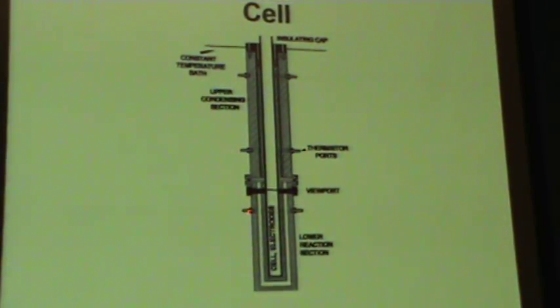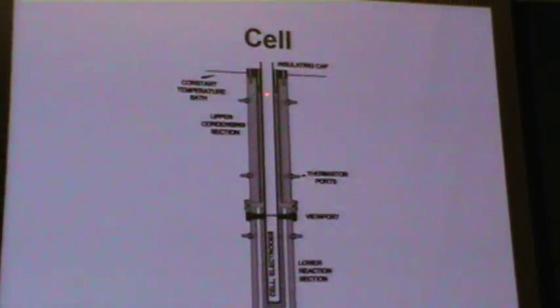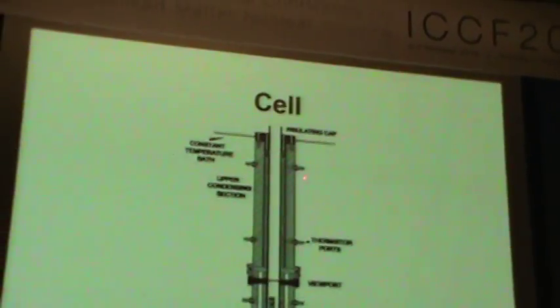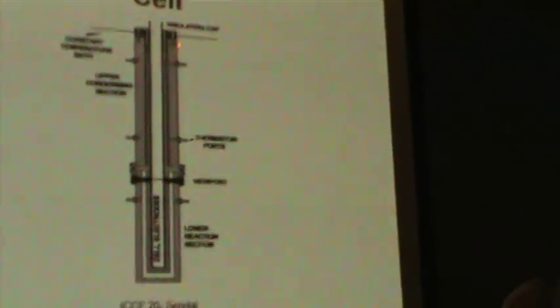So there are three levels of temperature measurements, inside and outside of the casing, which is aluminum. The outside, the whole thing is a constant temperature bath. So the outside temperature is constant, but the inside temperature varies. So the bottom is the hotter place. This is a little cooler and a little cooler there. There's a viewport so you can check the level of water in the cell.